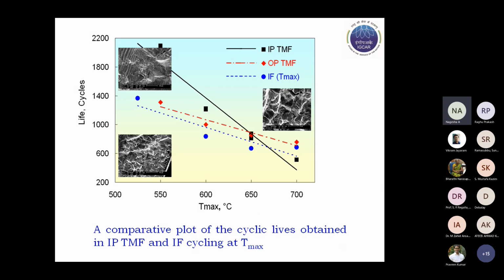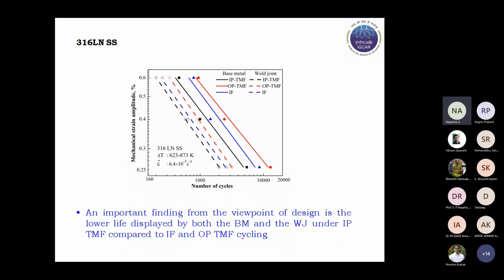Whereas in the cyclic life versus maximum temperature plot, we see that below a temperature of about 650 degrees centigrade, out of phase led to a lower cyclic life compared to in phase. Whereas with an increase in temperature beyond 650 degrees centigrade, in phase TMF gives rise to a lower life compared to OP. What is happening is, with an increase in the temperature, the creep deformation was found to be more pronounced, leading to a life reduction in comparison with the out of phase.